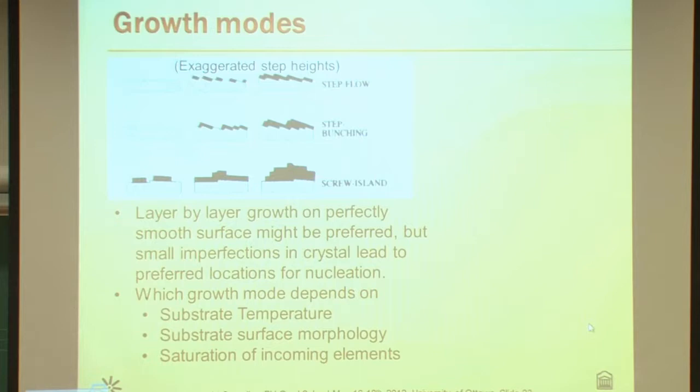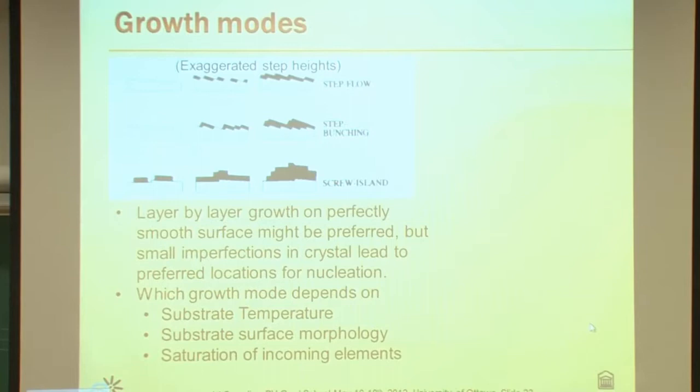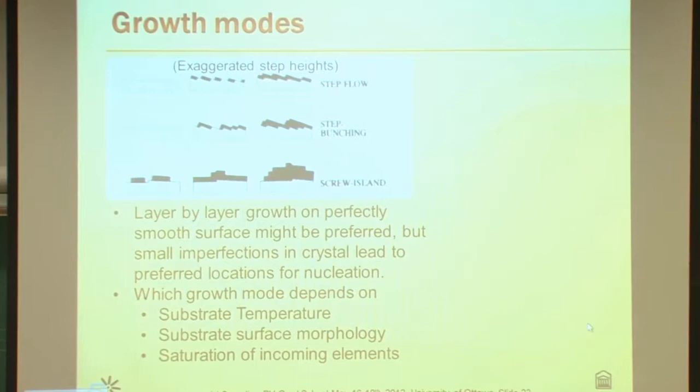It's called step flow. And I have another graphic that's going to show that nicely. But in general, the growth mode depends a bit on your substrate surface morphology, the substrate temperature during growth, and your saturation of incoming elements. How much material are you throwing at this substrate? How quickly is that growth rate going?